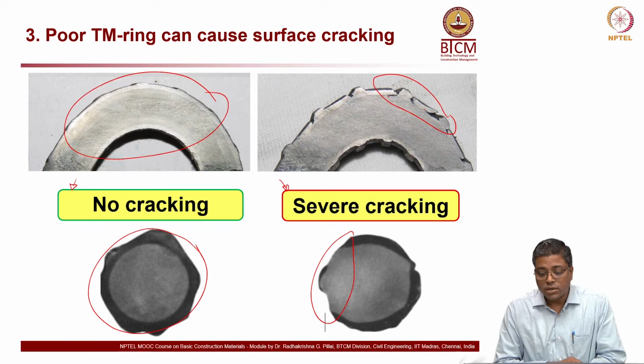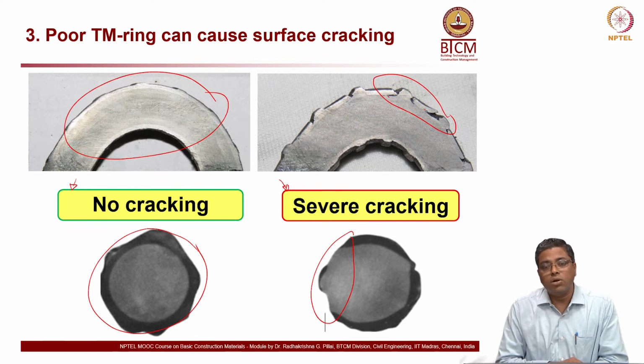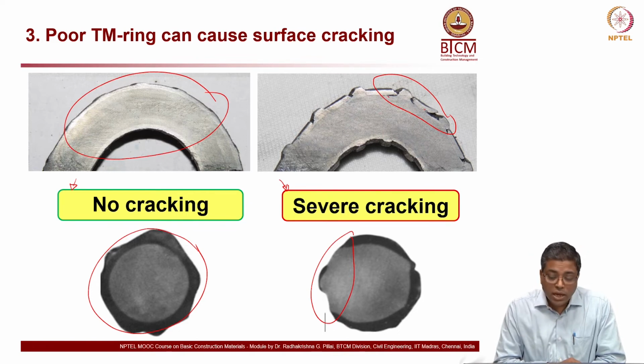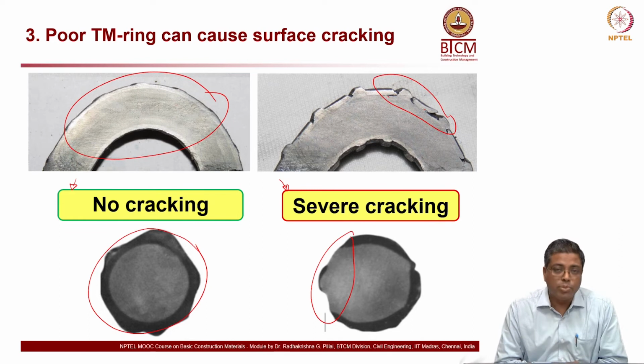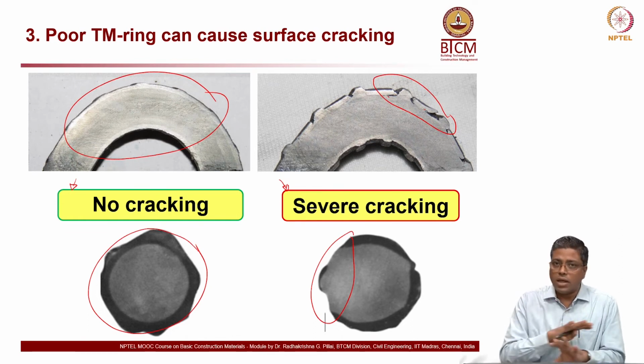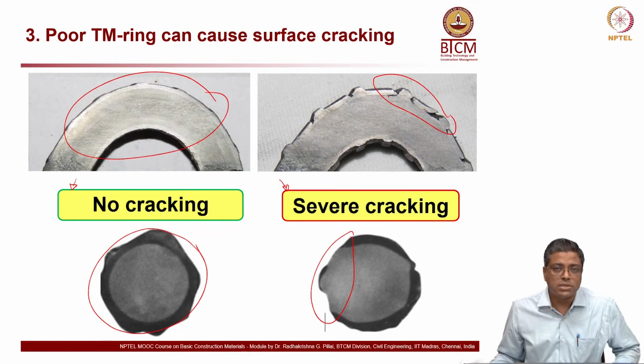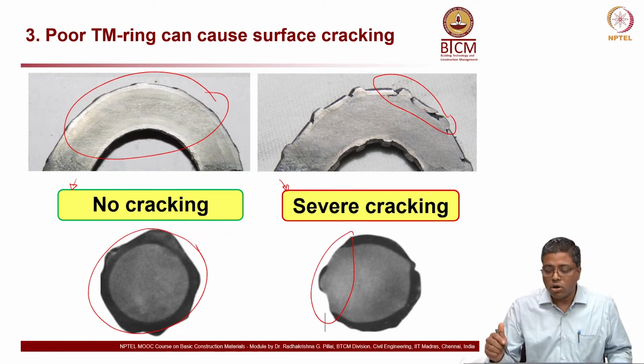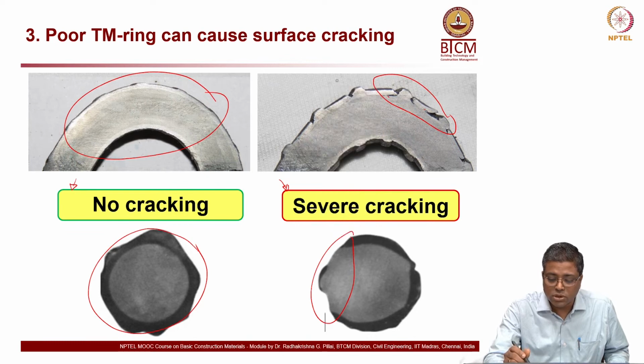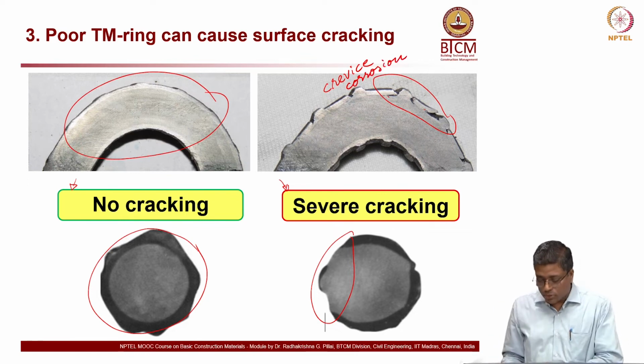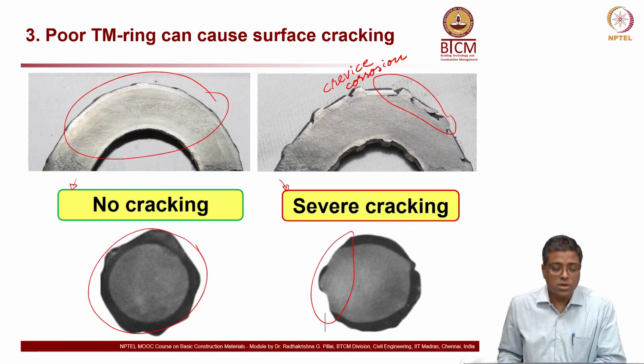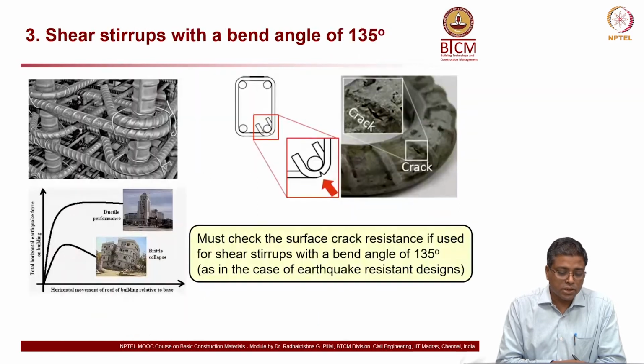Okay. And this is, I think, one of the reasons why a lot of the new construction starts corroding faster. Because if this kind of cracks are happening, you don't need chlorides, nothing. Only water and oxygen is essential. That is all that is required to cause corrosion, because the mechanism of corrosion is called crevice corrosion. Okay. This is what is going to happen if you use this kind of bars. So you must do this TMT ring test on all the bars which you get, a representative test.